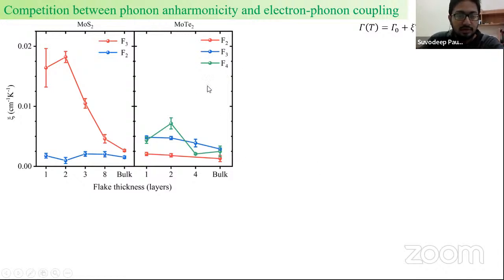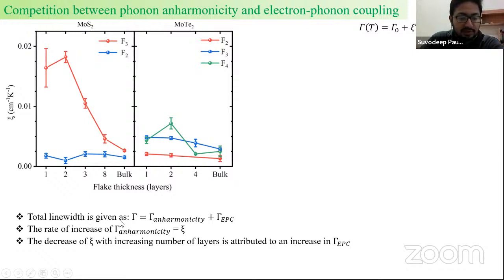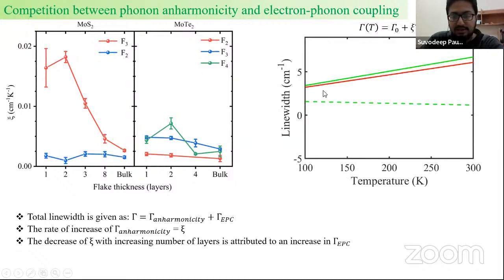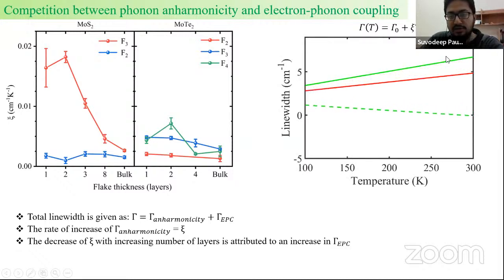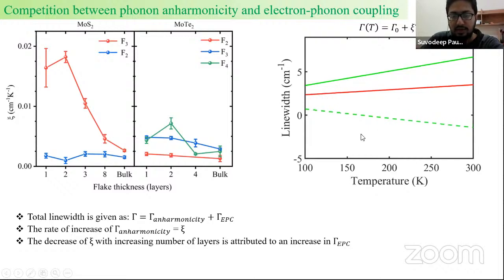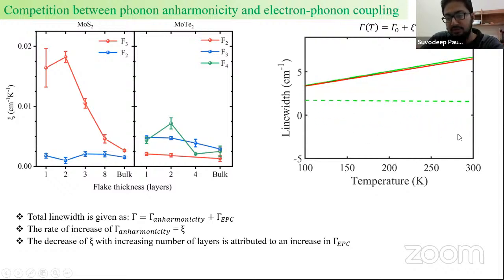So now we would discuss the line width here. The line width, as we had already seen, also shows an increase with temperature, and these are the linear equations with which we fit them. And the xi values again give us the slope and therefore the strength of anharmonicity. We must remember that the line width of a mode constitutes contributions from anharmonicity as well as electron-phonon coupling. So in this GIF, we see that this green solid line represents the anharmonic line width trend, and the EPC is represented by this dotted line.